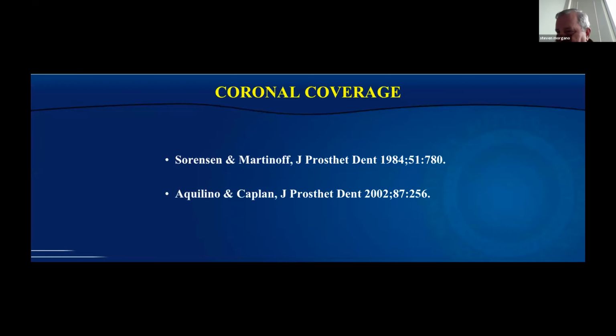They didn't find that with anterior teeth. Anterior teeth that could be restored with composite resin did just as well as those that were restored with crowns. Aquilino and Caplan also did a retrospective study, and they didn't separate the teeth out into anterior or posterior. They just looked globally at whether the tooth was endodontically treated and had a crown or not. And what they discovered was a tooth that was endodontically treated without a crown, 6 to 7 times the potential to fail.